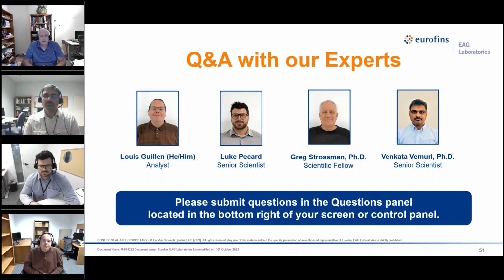Can we measure, or Venkat, can we measure the concentration of oxygen in material with RBS? Yes, we can. We can measure oxygen in the oxide materials, but the detection limit will be higher. As I said earlier in the presentation, oxygen has a lower cross section, and it also depends on the substrate material. The substrate material can saturate the oxygen signal.